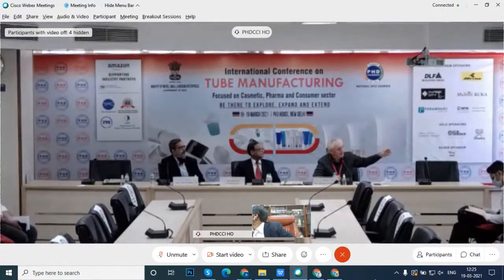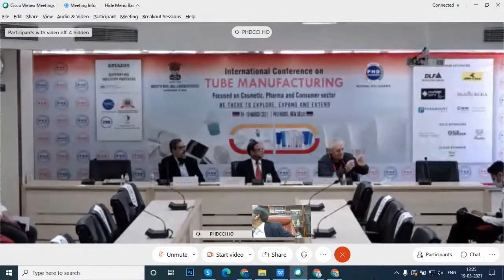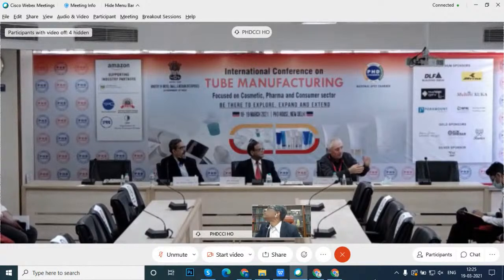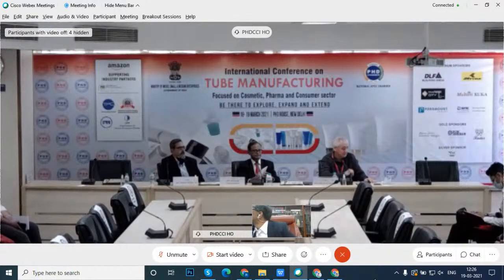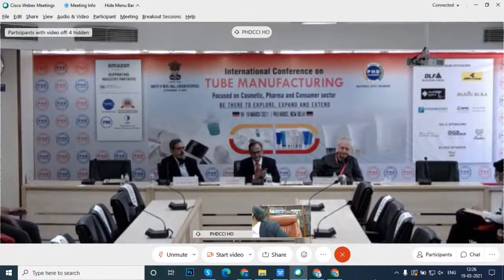As you have seen, the tube is pulled from the mandrel, and immediately the head of the tube goes into the holder before it leaves the mandrel on which it was made. So there is not even a fraction of a second where the tube is free. It's really very important for thin material. If you have thick material, a stable tube, okay, you may use many ways to transfer, but here you cannot. Okay, so thank you.